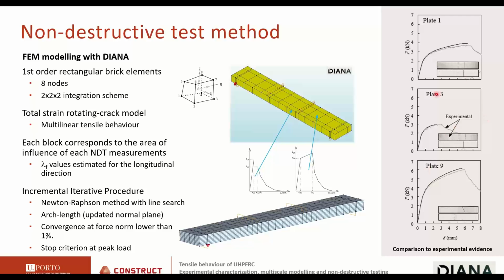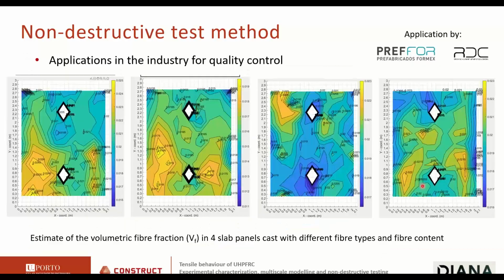And here you see the results of the simulations of some points. In some cases, the agreement was very good, as I show here. In others, not so much, but typically the agreement is quite good. So the outcome of this is that we can get data from NDT that can be used in finite element simulations to get the real behavior of the material as placed in the structure. This method is being used by the industry already.